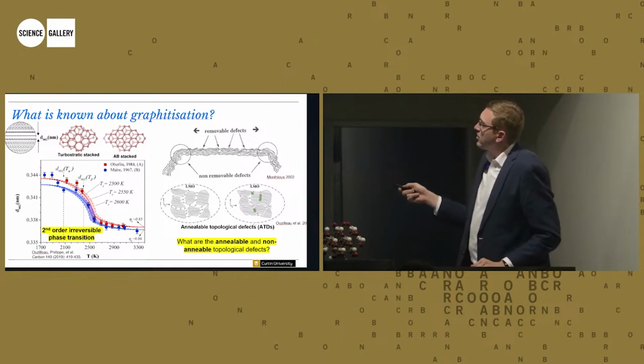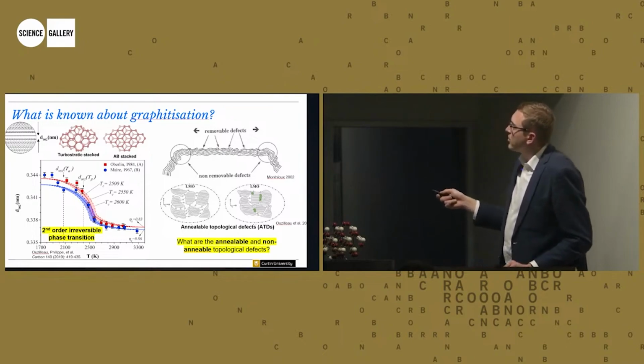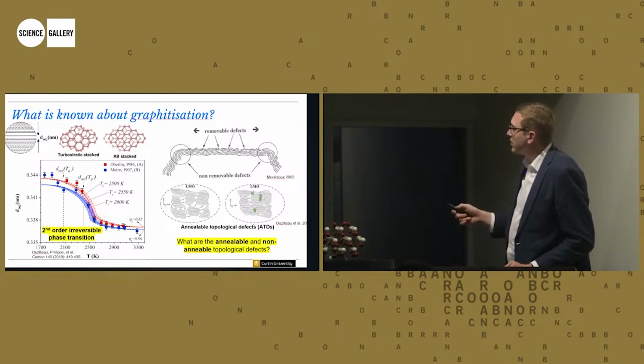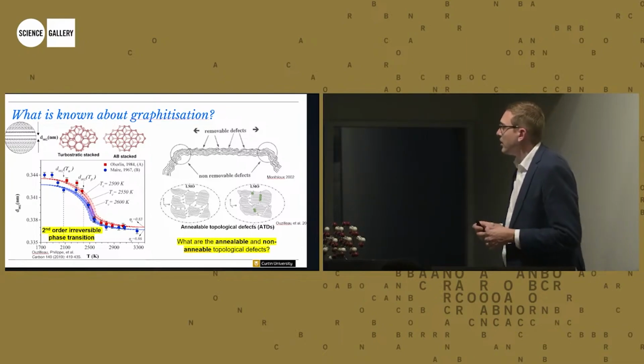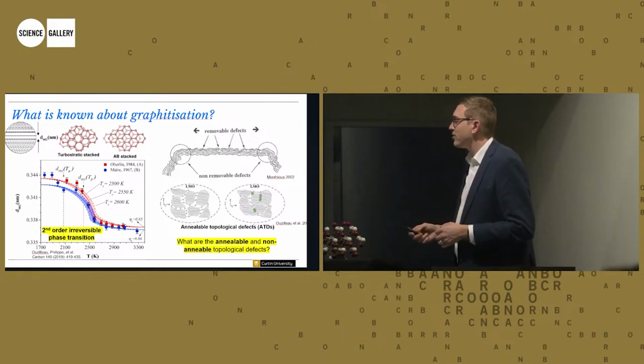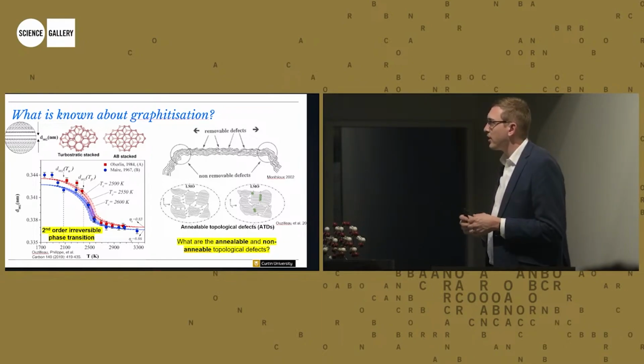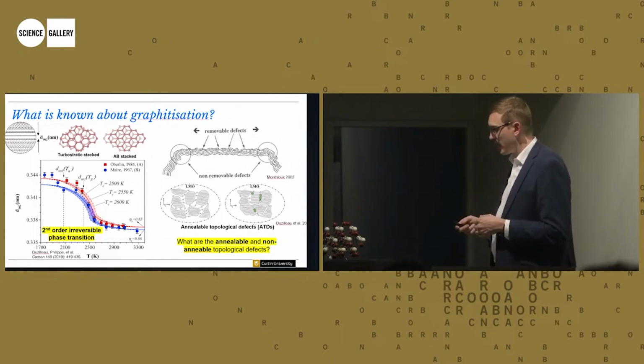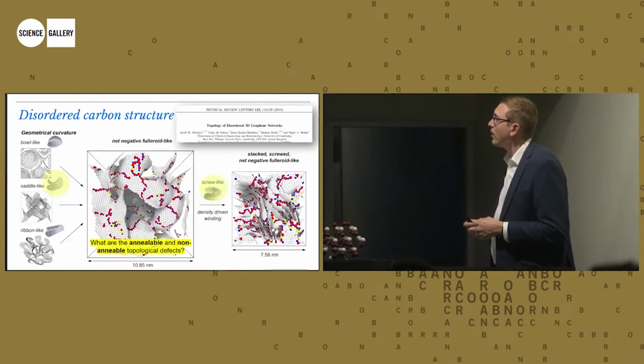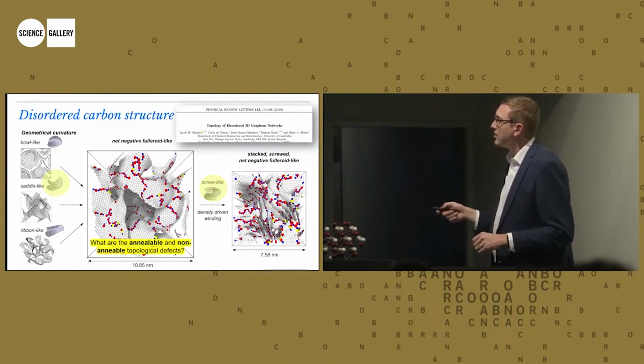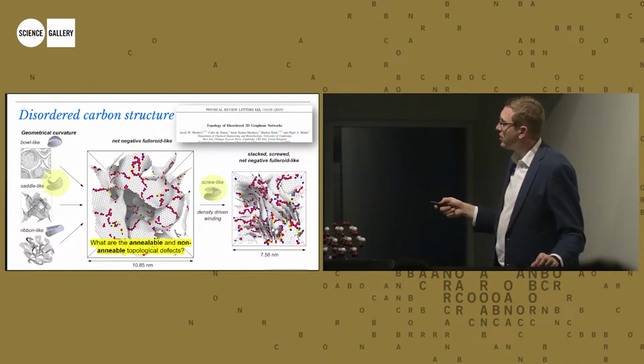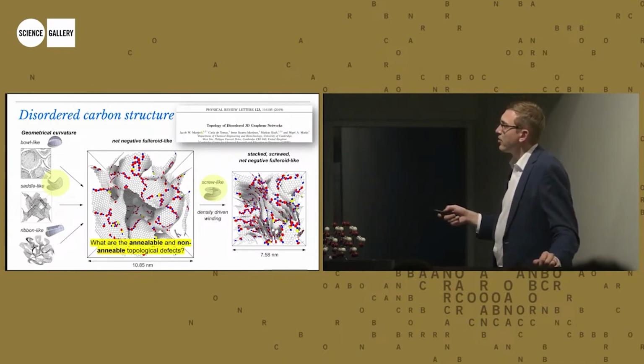There's been a suggestion that there are some removable defects, but there are also some non-removable defects. We call these topological defects. Topology is a fairly nebulous term, but it just means that there's some shape or some sort of bonding motif that makes these hard to remove. The first contribution that we made was understanding the structure of the disordered carbons. These here are models of disordered carbons. This is more of an activated carbon structure, and this is more of a glassy carbon structure on the right.